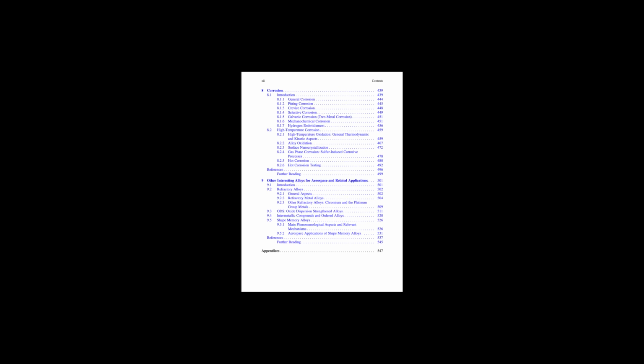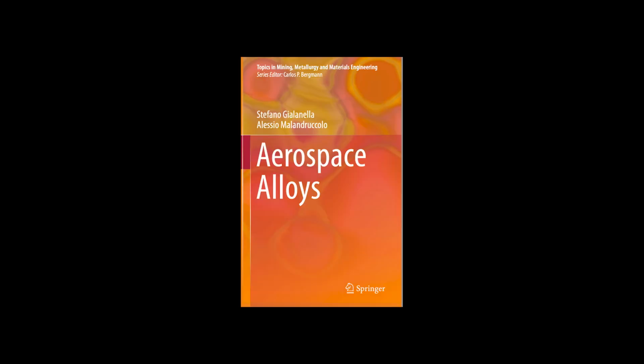Abrasive and abradable coatings. These are used for clearance control in rotating machinery. Right, like between the tips of turbine or compressor blades and the engine casing. To keep the gap really tight. Exactly. Tight clearances mean less air leakage, which improves efficiency. Abradable coatings are applied to the stationary part, the casing. They're designed to be soft enough that if a blade tip rubs against them, the coating wears away preferentially without damaging the blade tip, essentially allowing the blade to machine its own path.